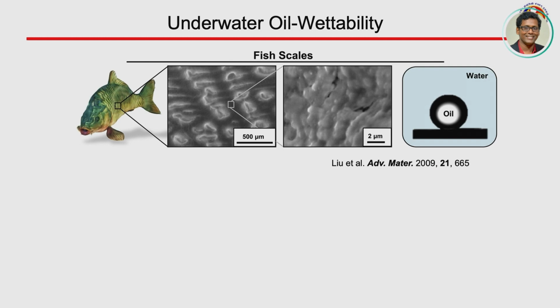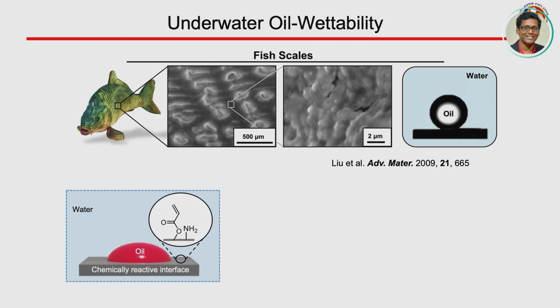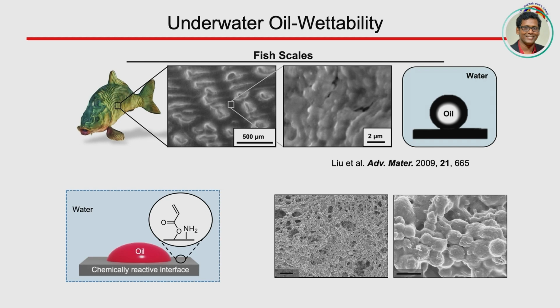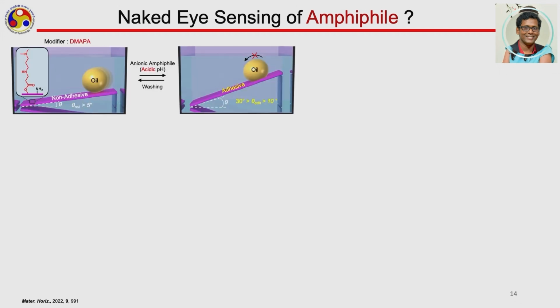Also some multi-layer coatings derived from polyelectrolytes. But they are not good in terms of durability. They often suffer from durability problems. So we thought, why not use this covalently cross-linked polymeric coating, which remains chemically reactive, and explore this porous coating in designing an adaptive superoleophobic interface. And the key contributor of this work is sitting here in the audience, and she took this challenge and developed these adaptive coatings. Adaptive coating means here that for this superoleophobicity, you can precisely play with the adhesions. And when you play with this adhesion, that gives you a platform to visualize amphiphilic molecules with the naked eye.